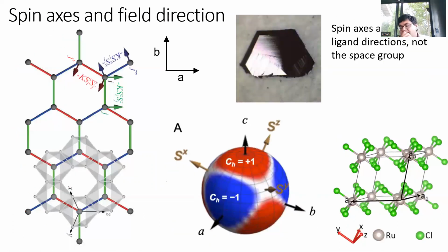that we did. One important point to understand going forward for the last part of my talk is that it is extremely important in which direction you apply the field in this sample. As it turns out, this is a topological material and it has a non-zero Chern number, but that Chern number is non-zero not for all directions of the field. So it turns out that if this is your lattice, then you define this axis as the b-axis. So this is the armchair axis. And then this is the zigzag axis, which you call the a-axis. So it turns out that you have a non-zero Chern number only when you apply your field along the a-axis or along the c-axis, but you don't get a non-zero Chern number when you apply the field along the b-axis.